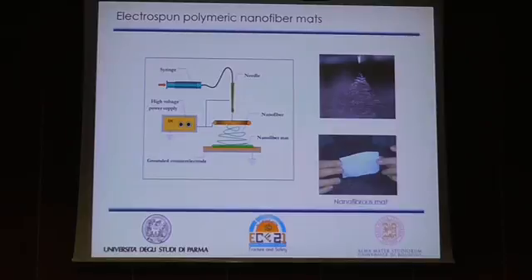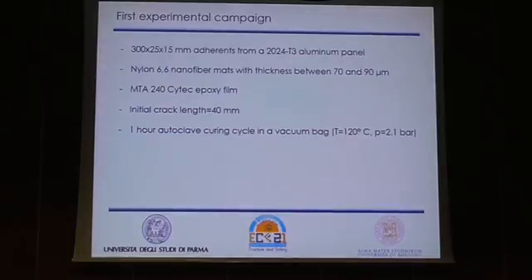In the current case, our mat has a thickness included in the range between 70 and 90 micrometers, while the nanofibers have a diameter of 150 nanometers. A first experimental campaign is now discussed.